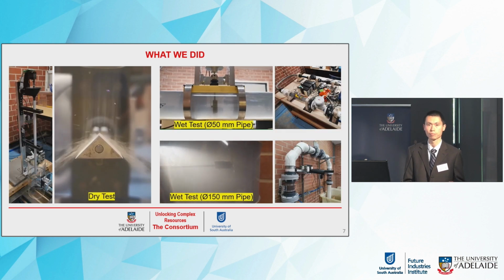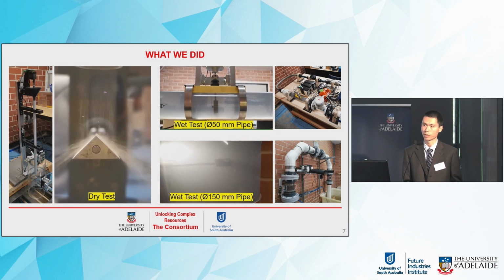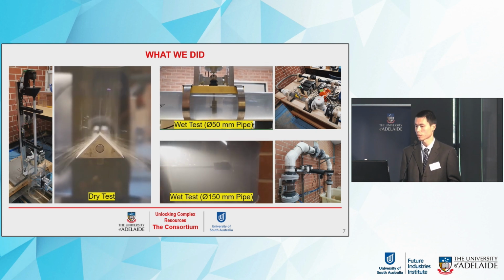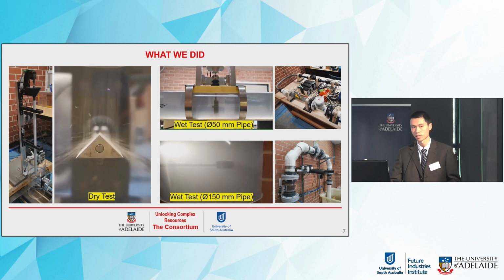To understand the probe response under particle impact, we started with testing in dry conditions. And that has shown to be useful in applications beyond hydrocyclones. I will cover that in more detail shortly. After the dry test, we moved on to more complicated scenarios involving slurry in a small-scale closed-loop flow system. And to test the scalability of the sensing system, we have also done some tests on a larger-scale closed-loop flow system.